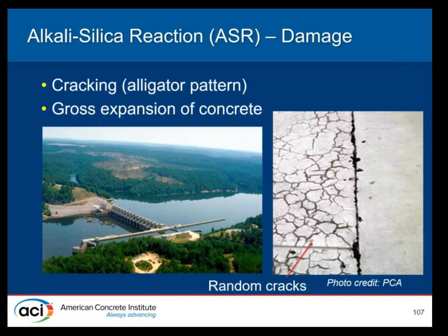The expansive reactions from ASR typically have a map cracking or alligator pattern, and that's a result of the expansive reactions at the aggregates causing that popping to occur. In the pictures, there are two slabs, one's cracked, one's not, at Tuscaloosa Lock and Dam. It's concrete with different cements. One had a high alkali content, the other a low alkali content. And that difference in the alkali was the material driving the reaction, allowing the aggregate to react in the one and not to react in the other.